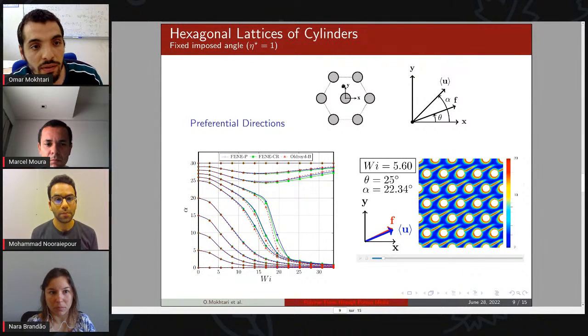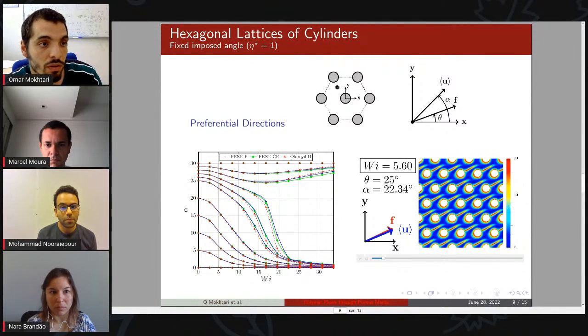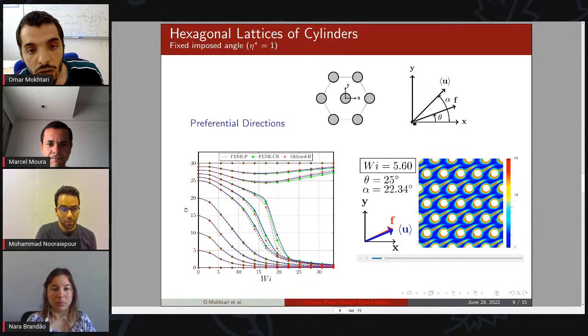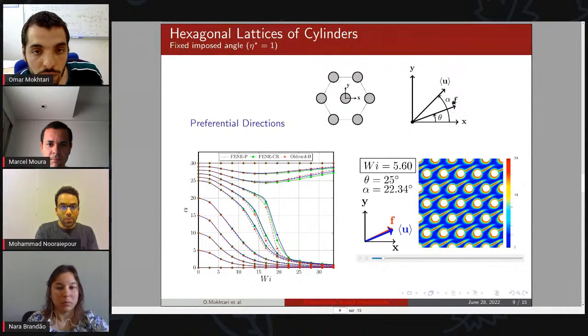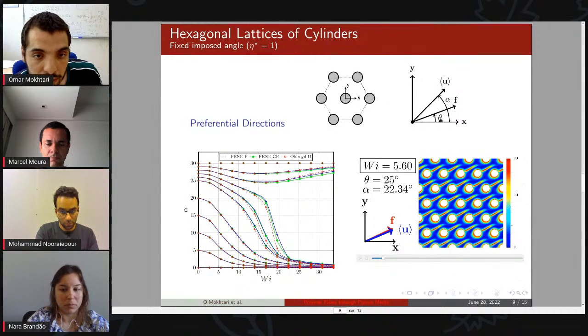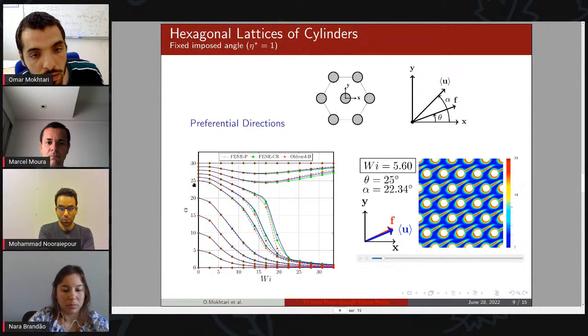We consider numerically this hexagonal lattice of cylinders. We impose a flow-driving force F with a fixed angle theta, and we increase the Weissenberg number through the magnitude of F. If I consider, for example, the case theta equal to 25, we can see that the mean velocity angle, which is alpha, decreases until 0.